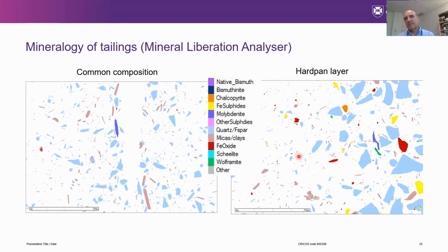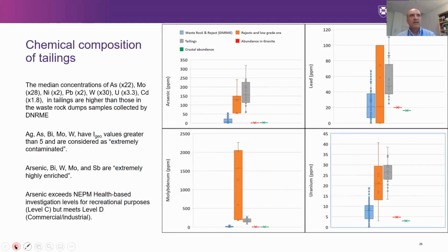So this hard pan layer is better because it's more concentrated. So you get more concentrations of molybdenite, which is very common on that site. But we also have wolframite and a very, very small amount of scheelite. So this site is not a scheelite site, it's a wolframite site. But there are sites in other parts of the world with tungsten tailings that have a lot of scheelite in them, for example, in Sweden.